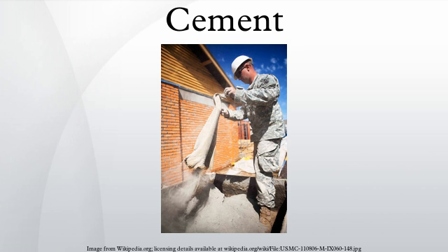Portland fly ash cement contains up to 35% fly ash. The fly ash is pozzolanic, so that ultimate strength is maintained. Because fly ash addition allows a lower concrete water content, early strength can also be maintained. Where good quality cheap fly ash is available, this can be an economic alternative to ordinary Portland cement. Portland pozzolan cement includes fly ash cement, since fly ash is a pozzolan, but also includes cements made from other natural or artificial pozzolans. In countries where volcanic ashes are available, these cements are often the most common form in use. Portland silica fume cement.